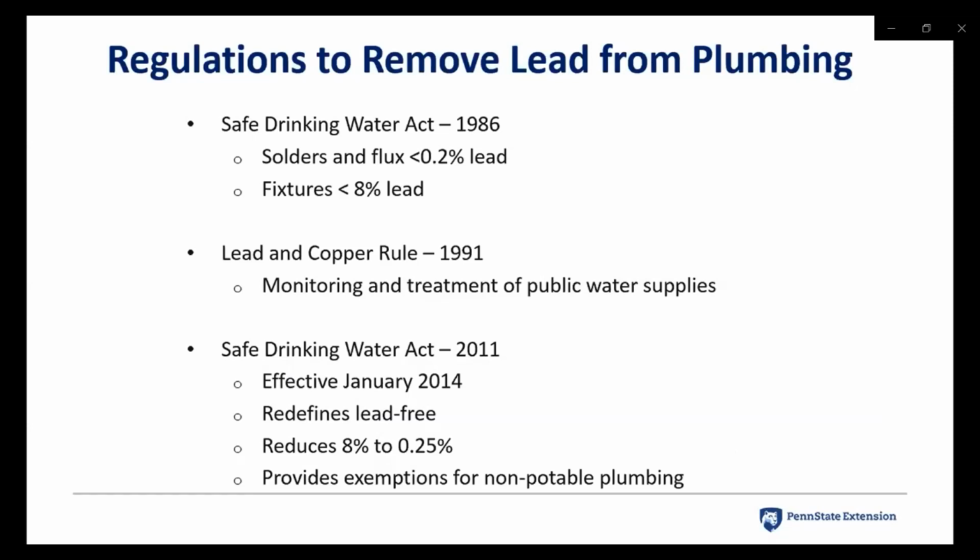One of the reasons for that was we were noticing a lot of new homes that still had fairly high lead in their first draw sample, and it was coming from the faucet. If you think about it, that little bit of water that you collect in a first draw sample is dominated by what's in the faucet and the first few feet of pipe below that. So the faucets and the fixtures become very important when you're looking at a first draw sample.